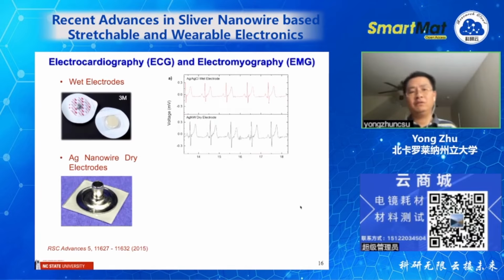And then also this electrode, because we said that this material is highly conductive, right? So we just use it as an electrode. This is the commercially used 3M electrode, which you may see in the hospital. It has a gel layer, which is important to ensure the quality of the electrode-skin interface, but that causes some problems like skin irritation. So there's a strong need for so-called dry electrodes without the gel layer.